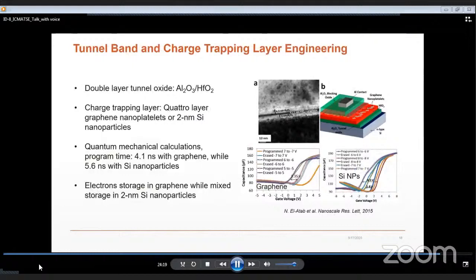I have also worked on combining both the tunnel oxide engineering and charge trapping layer engineering. In this work, aluminum oxide and hafnium dioxide are used as a tunnel oxide, while both graphene and silicon nanoparticles are studied as the charge trapping layer. And using quantum mechanical calculations, the program time is found to be a few nanoseconds due to the tunnel band